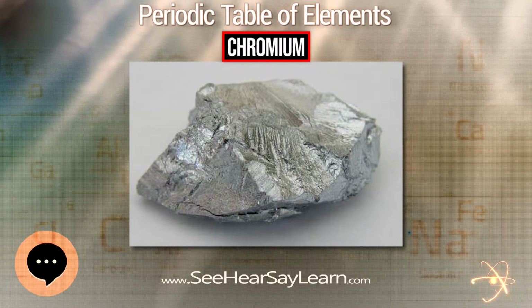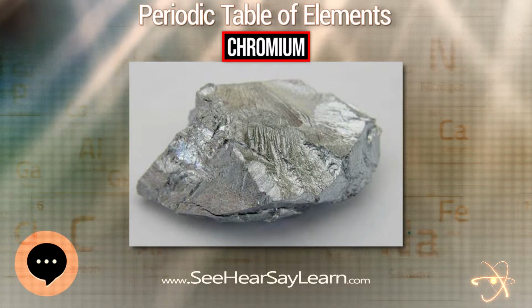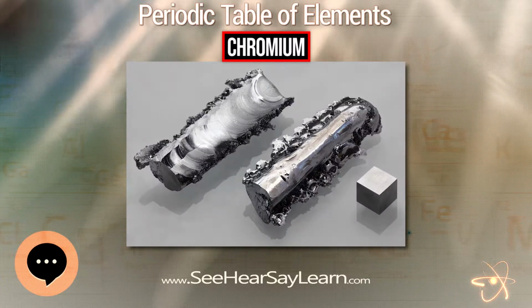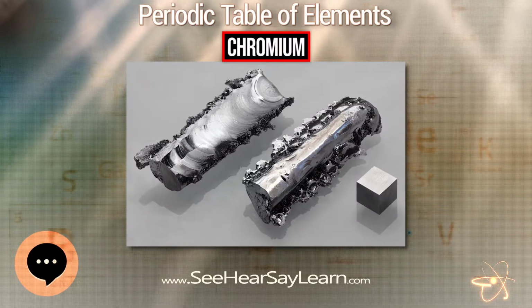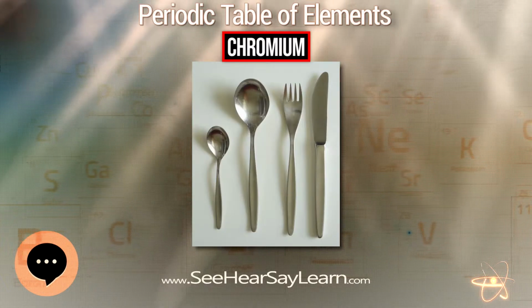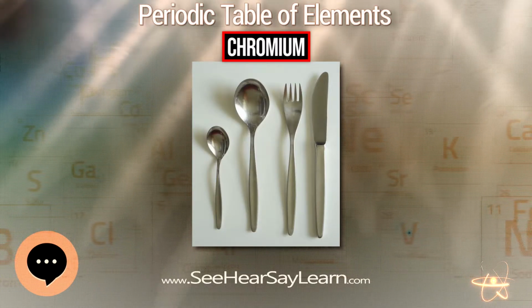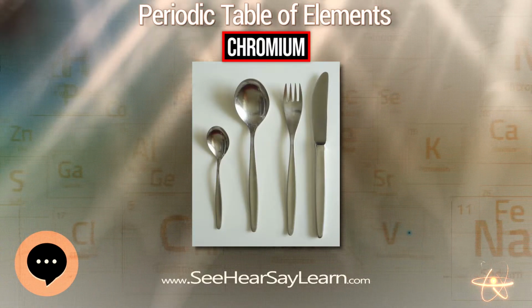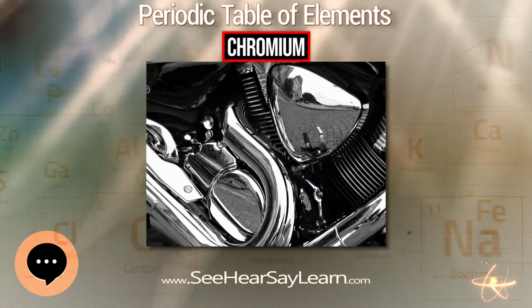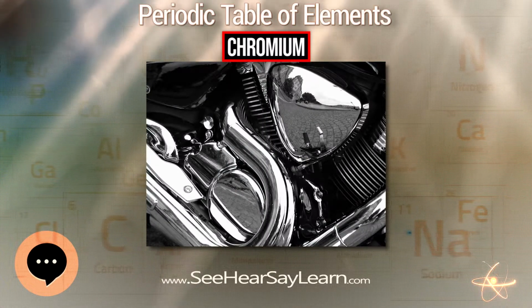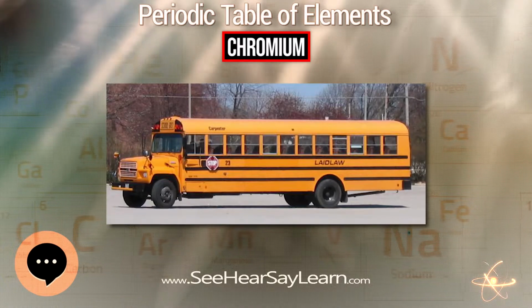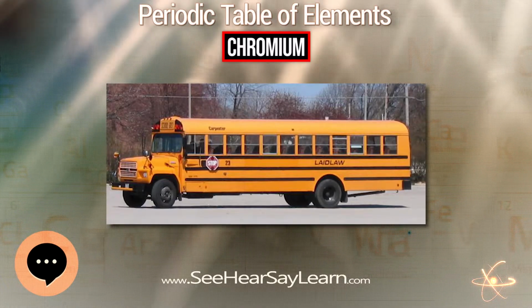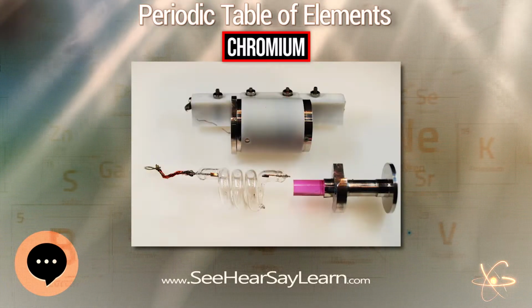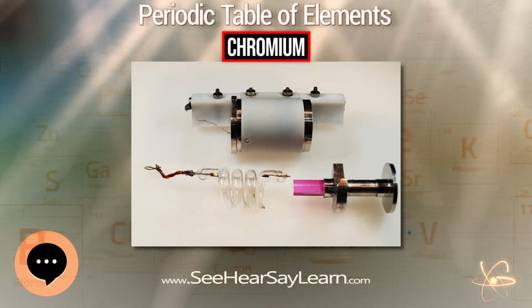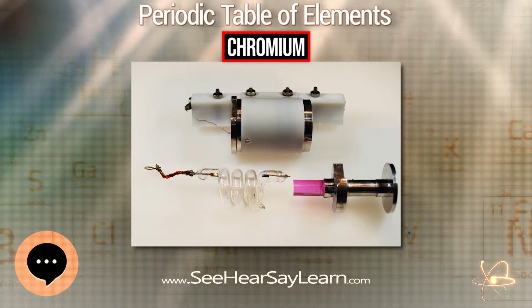Thin deposition involves a layer of chromium below 1 µm thickness deposited by chrome plating, and is used for decorative surfaces. Thicker chromium layers are deposited if wear-resistant surfaces are needed. Both methods use acidic chromate or dichromate solutions. To prevent the energy-consuming change in oxidation state, the use of chromium sulfate is under development. For most applications of chromium, the previously established process is used.